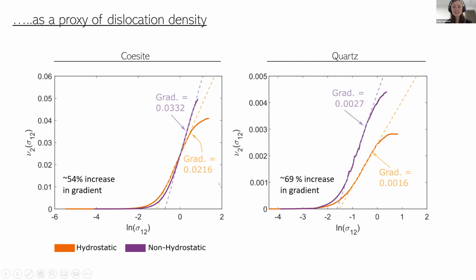And the only thing you really need to know about this is that if that internal stress heterogeneity is the result of dislocations which are formed due to deformation, then you'll have a straight line at high stresses, which is what we're getting in all of these situations. And also the gradient of that line will depend on the amount of dislocations that you have in there. So we aren't able to get an exact number on dislocations yet, but we can quantify that we have a higher number of dislocations within that sample that was going through the transient plasticity comparative to the hydrostatic